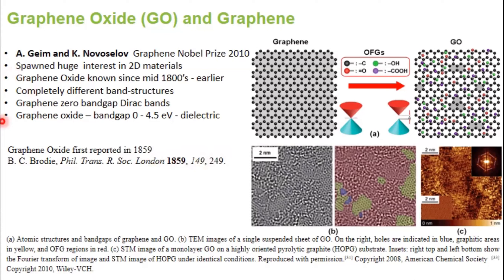The materials are very different even though they both contain carbon lattices. Graphene is a rigorously two-dimensional material with amazing properties and a Dirac band structure, whereas graphene oxide is much more complicated with functional groups, giving it more of a dielectric behavior with a finite band gap that can be tuned by various means. They're complementary — two sides of the same coin.